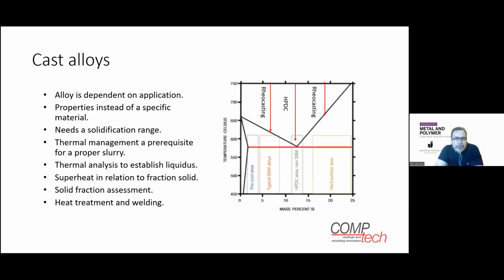Yep. The alloys then. This is probably the biggest change if you compare with conventional high-pressure die-cast parts, which usually use eutectic alloys, I would say between 9 and 12% of silicon, right in the middle here. That means that we have a very small process window for making the slurry, because we live on the distance from the liquidus line down to the solidus line. And here we would like to have a long distance, compared to what we get with the high pressure die casting alloys.